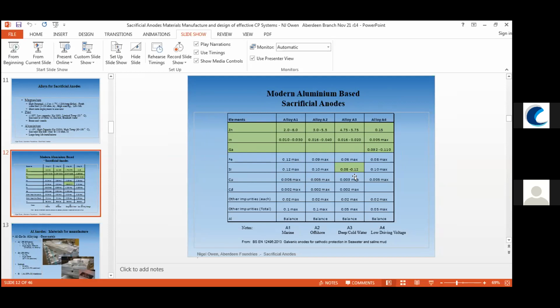One of the main issues with making anodes in the first place was trying to get the source ingot, a very high grade ingot, which would have very low iron and low copper, because those two elements tend to interfere with the stability of the anode and they cause passivation, etc. So for these deep water alloys, and say alloy A3 with high reliability, we're using less than 0.06 iron for those applications, and they've used the anodes down at 3,000-4,000 meters, I believe, and these can be relatively stable.